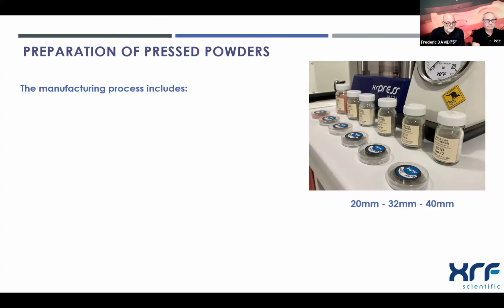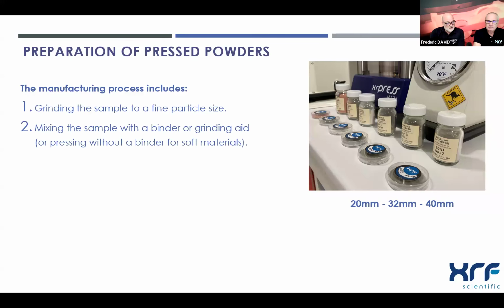So again, the manufacturing process includes grinding, so grinding the sample to a particular size. I will not go into details of all the equipment available for that because it's another long topic. Of course, mixing the sample with a binder or with a grinding aid, or sometimes it's not needed if the material is soft enough. And of course, pressing the sample, the specimen, between 2 and 40 tons.